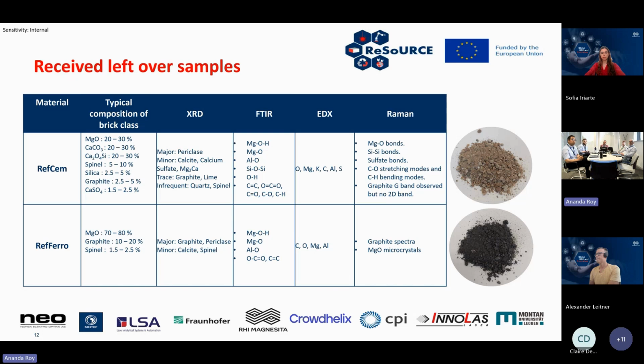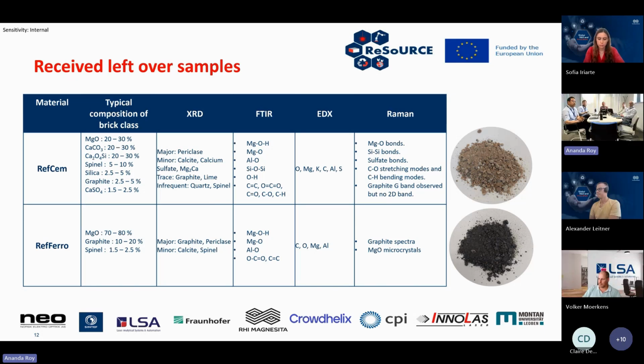We have a typical composition of the brick class for both this RefCem material and the RefFerro material. And they differ slightly. The RefCem material has slightly more calcium species in it, whilst the RefFerro material is a bit simpler with magnesium oxide, graphite, and spinel. Generally, across our different characterization techniques, we see the materials present that we would expect from the initial composition of the brick class.